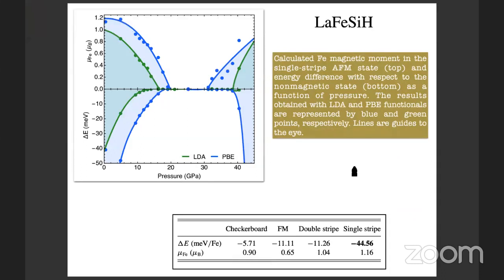So our theoretical collaborators did the density functional calculations, and after that they calculated the energy differences and effective magnetic moment for the different states, like the checkerboard model, the FM model, the double stripe antiferromagnetic and single stripe antiferromagnetic models. But it is interesting to note that the single stripe antiferromagnetic model always gives the minimum energy. So we can say that the ground state of the system is single stripe antiferromagnetic.